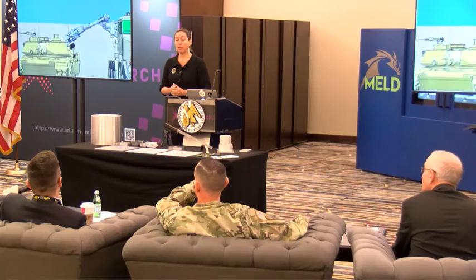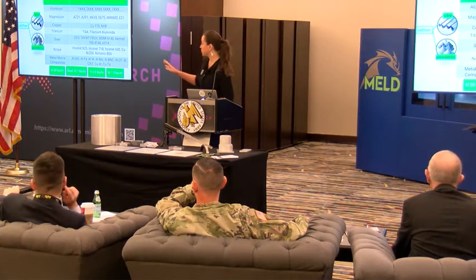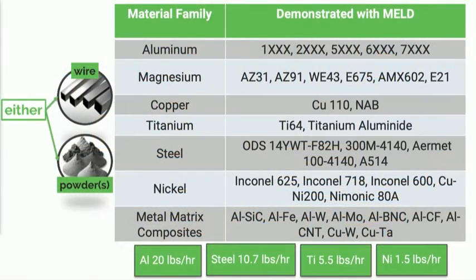Okay. And then just in terms of deposition rate, as an example, how long did it take to build the missile housing there? Yeah, so deposition rate, we have about 20 pounds per hour. And actually, I can show you, these are the materials we've processed ourselves and some deposition rates. When you're in aluminum and magnesium, we can put down a lot of material. When you get up into steel, air mets, we're going to go a bit slower, but still overall, this is very scalable, well-suited to make big things with a lot of metal.